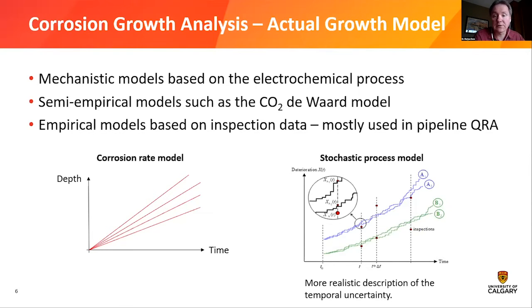Or we can use so-called stochastic process models, where we say, okay, at the time of the inspections, we know how much metal loss we have in the pipeline. And we're just worried about how much the jump or the increase in metal loss is from one inspection to the next. How we get from one inspection to the next, what the exact shape of the metal loss is, if it's linear or non-linear or any other form, doesn't matter. So if you compare the corrosion rate model on the left with the stochastic process model on the right, the stochastic process model from an uncertainty perspective is really the right way of analyzing ILI data.